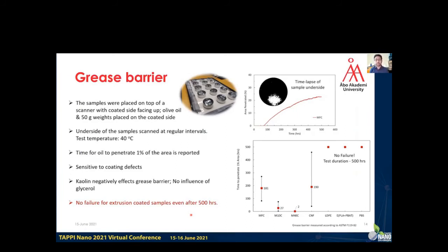So what we did was we replaced the glass plate with a scanner that scans at regular intervals, and then we take all the images and process them through an image processing software that gives an image like the one on the top right, showing area penetrated as a function of time. We take the time for oil to penetrate 1% of the area as failure. And on the bottom, we can see the time to penetrate 1% area for different coated samples.